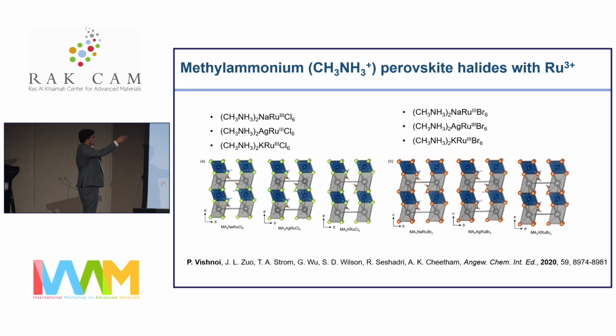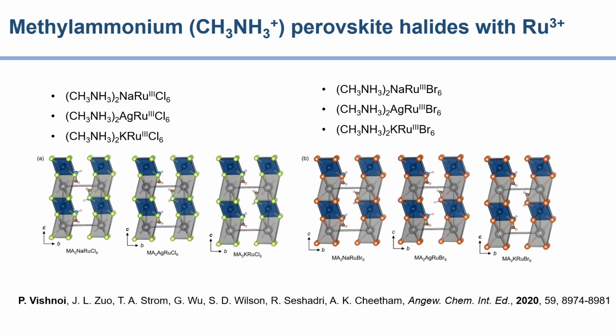So what we obtained in all these three compositions is the same structure type. And not only that, even if we change chloride with bromide, still the structure type is the same. It's a one-dimensional hexagonal lattice. Because there are about half a dozen structures which are forming one-dimensional structure, we thought of looking in more detail in terms of certain parameters,